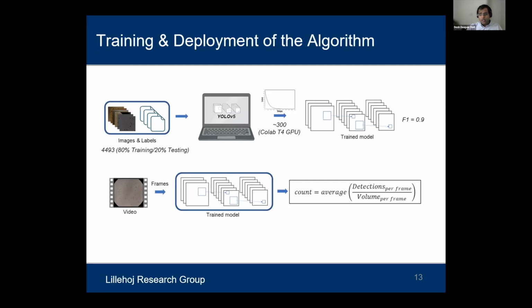We have samples, so we took a lot of images. We captured a lot of images. We trained a CNN algorithm. When I started this research, YOLO V5 was one of the fastest in inference speed. So we tested YOLO V5, and we almost had 4,500 images. We split that into 80-20 training and testing sets. We trained the algorithm on Google Colab's free T4 GPU, and then we used this model to do the inference.